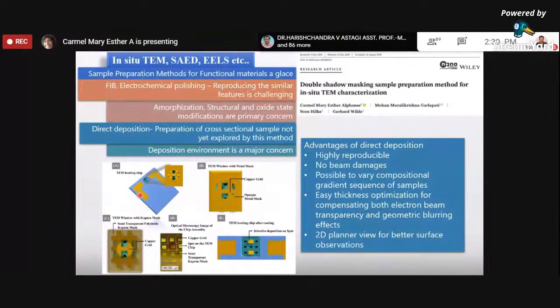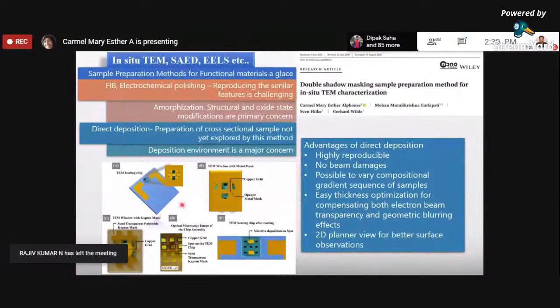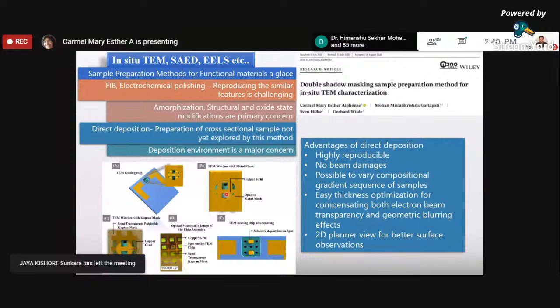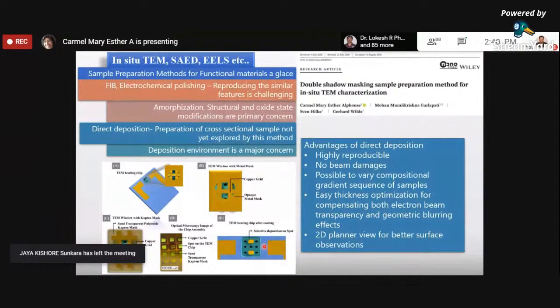Here we can see the electrical contacts. If these electrical contacts are damaged during sample preparation, it is very difficult to continue further. With all this in consideration, we placed a copper grid and kept another layer on it. It is a double masking, and we chose two specific windows and used this setup to develop a vanadium oxide thin film. This is a graphical illustration of how we can deposit a very small region layer on a specific part. In this optical microscope image, we can see this window is approximately 30 micrometers.